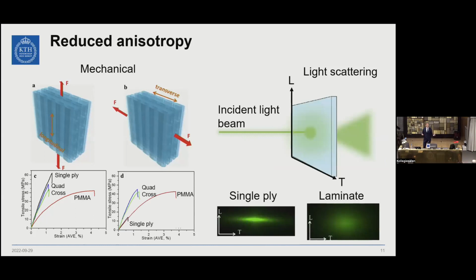We also checked the transparency, the effect of anisotropy on light scattering. You can see for single ply, it's quite narrow and oriented in the transverse direction, while for the laminate, it becomes more homogeneous in all directions, although we lose some transmittance.